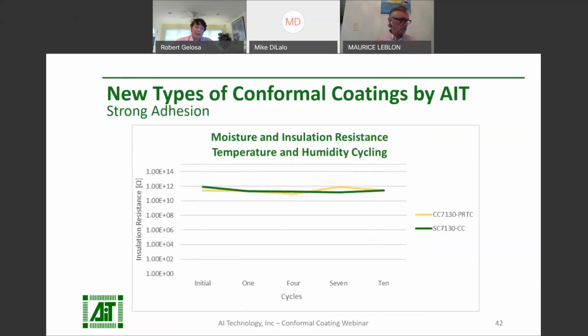AIT coatings have excellent adhesion. Even under temperature and humidity cycling, AIT coatings do not delaminate from the board and show no bubbles, pinholes, blisters, cracking, or other issues. We see the insulation resistance across a coated board does not change, even when subjected to temperature and humidity cycling. The water molecules are not able to displace CC7130 PRTC or SC7130 CC, so we see no change in resistance.